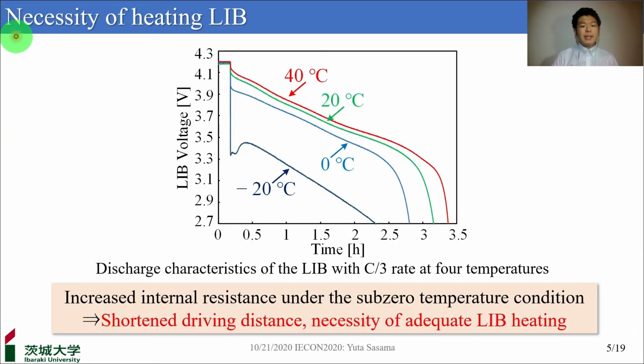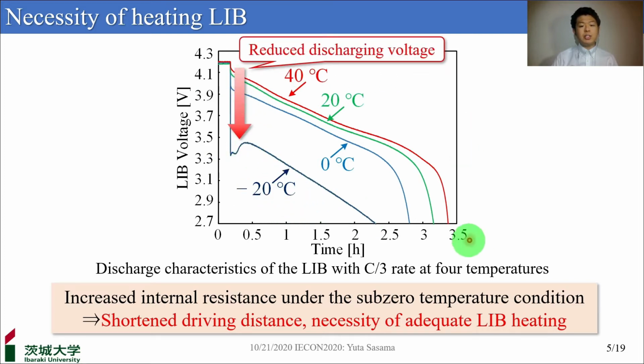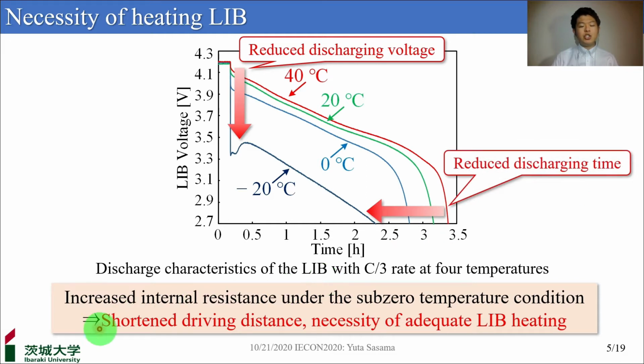Background. Let me begin by talking about the necessity of heating the battery. Here, you can see the graph about the discharge characteristics of the lithium-ion battery with a C over 3 rate at 4 temperatures. The horizontal line shows time and the vertical line shows the voltage of the lithium-ion battery. Focusing on the dark blue line of -20 degrees, you can see the reduced discharging voltage and time. They result in a shortened driving distance, therefore heating the battery is necessary for cold climates.